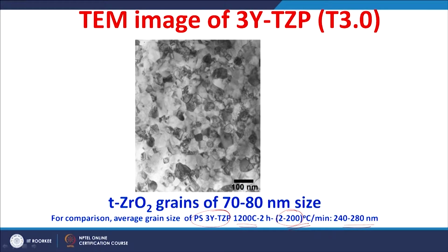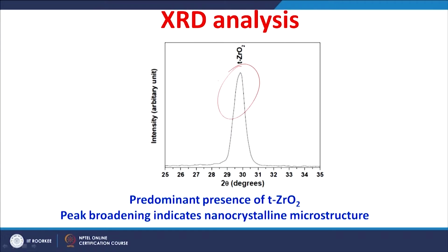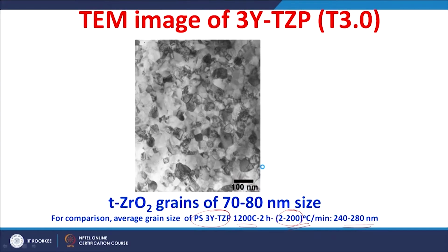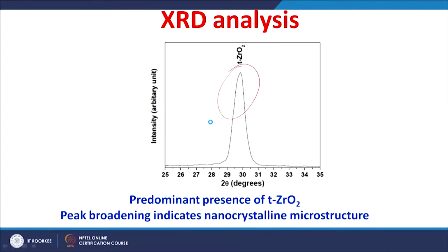So, you get tetragonal zirconia grains of around 70 to 80 nanometers, and all our XRD analysis also indicates the predominant presence of the tetragonal zirconia. We started with the tetragonal zirconia powder, and the same tetragonal zirconia is still retained even after the sintering. But we can also see the peak broadening, which indicates a nanocrystalline microstructure. The microstructure also shows the grains of around 70 to 80 nanometers.